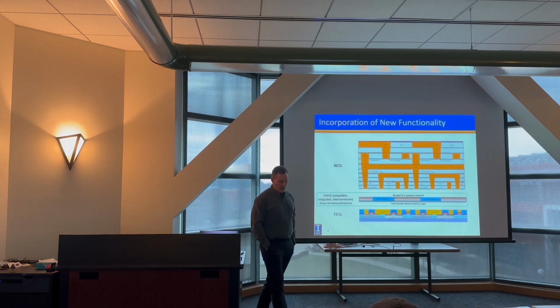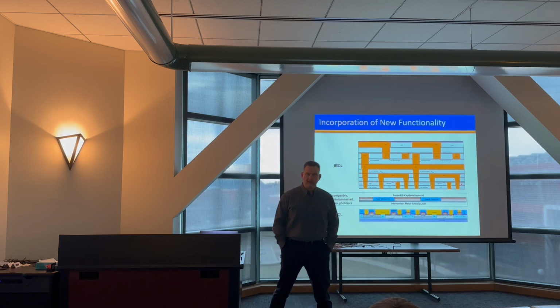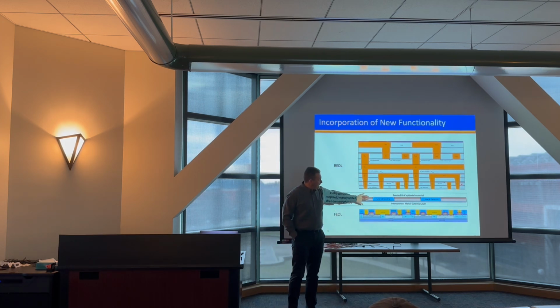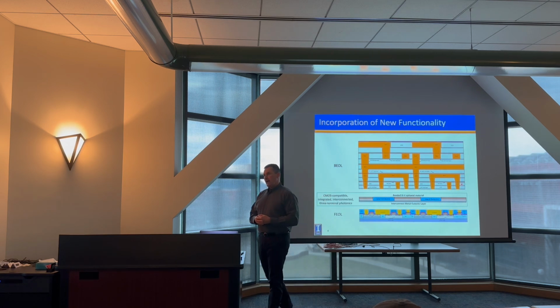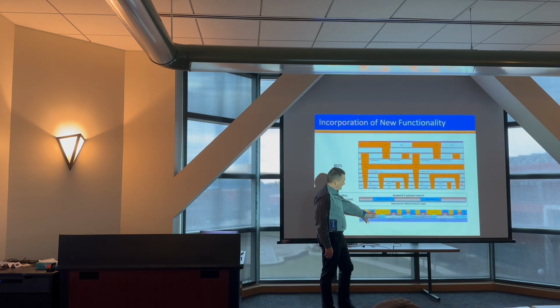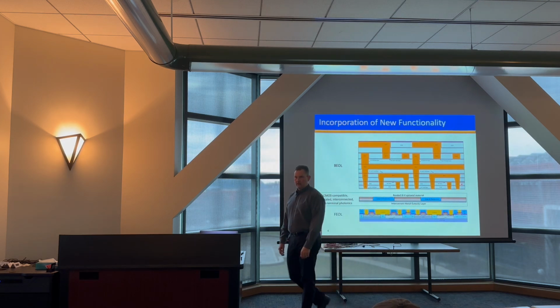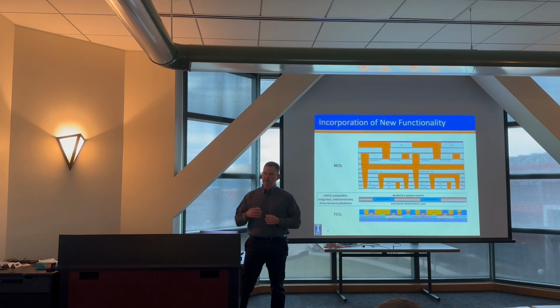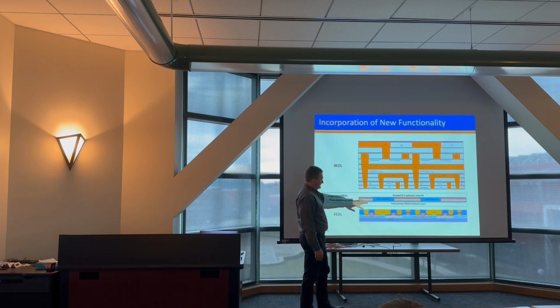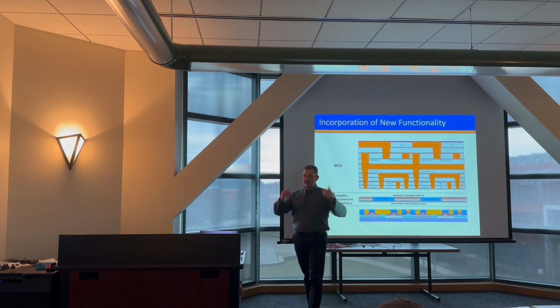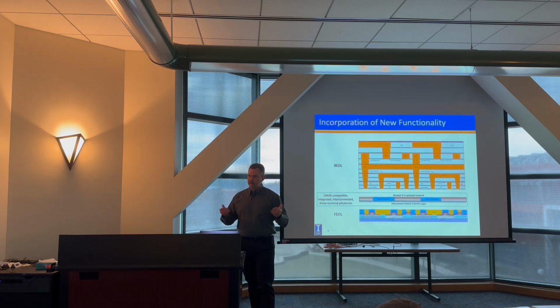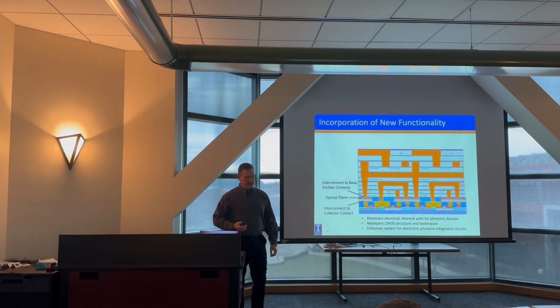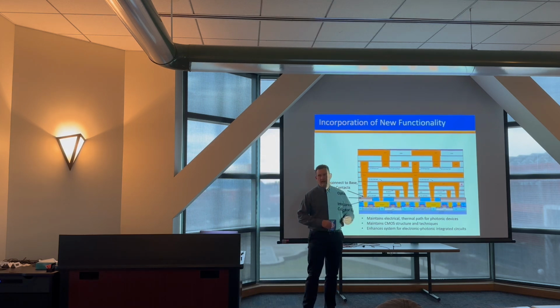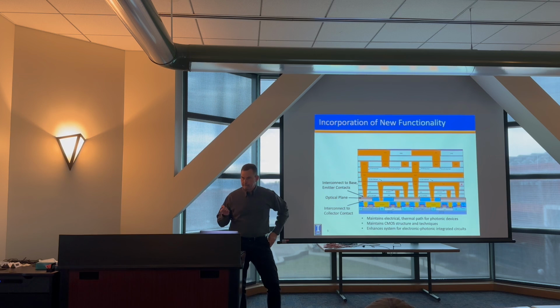And when we think about incorporating functionality of some kind, what would be ideal is if that were an actual layer in the CMOS stack. So we start by taking our wafer coming out of the front end of line process. We incorporate one or multiple layers that have some sort of additional functionality, 3-5 materials, etc. And then we build the rest of the stack on top of that. So we put all of our interconnect layers and everything, so that effectively what this becomes is an augmented integrated circuit that has this enhanced functionality embedded in it. And this is obviously where we'd like to be able to go eventually.